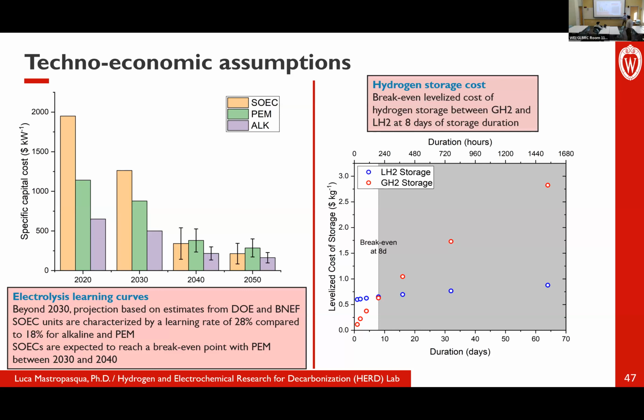Also, the other advantage related to this is that SOEC don't need noble metals as catalyst. So if you work at low temperature, the kinetics are very slow, and therefore you need an electrocatalyst that increases the reaction rates for your water splitting reaction. So PEM and alkaline need an electrocatalyst. PEM must use iridium and platinum as catalyst to increase the reaction rates of the process.